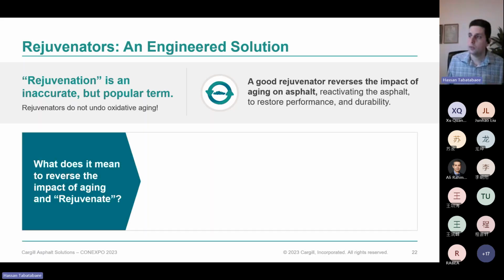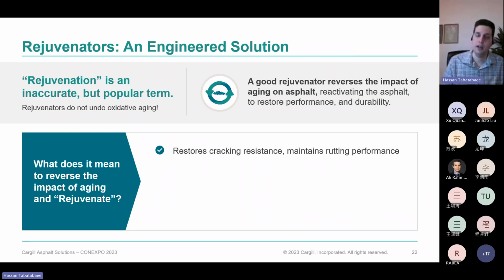What that would mean, ideally, is restoring the cracking resistance by overcoming that embrittlement that occurs in aged asphalt as it gels through the association of the more polar, heavier molecules, the asphaltenes, as they build up and become more prone to association in an aged asphalt.